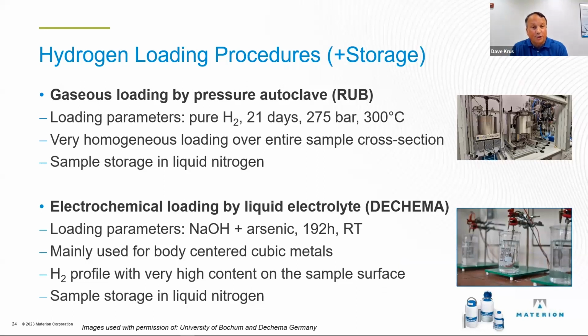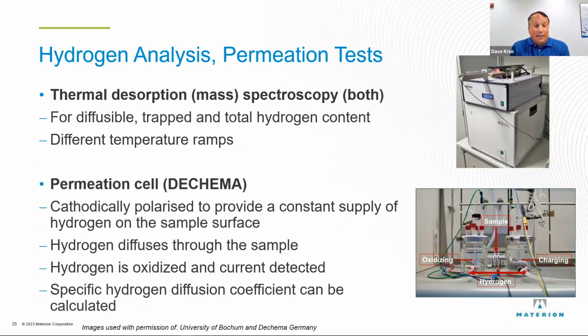And for a higher concentration of hydrogen at the surface, you use the electrochemical loading, and that's a sodium hydroxide and arsenic bath that it's in, which puts more H2 at the surface, and you would expect more loading, more hydrogen passing into the samples at that point. So the techniques that we used, we can give you details on this, but mainly what we're going to be talking about is the thermal desorption mass spectroscopy, TDMS, and that will give the total hydrogen content in the materials. There's also a permeation cell. I don't talk about that much in this presentation, but that shows how the hydrogen moves through the samples.